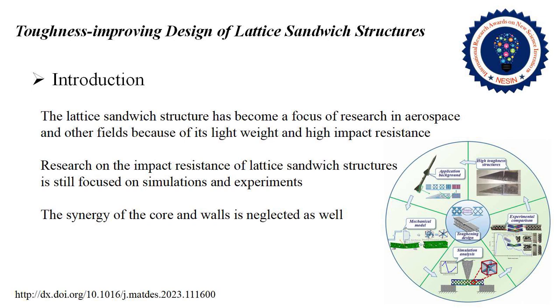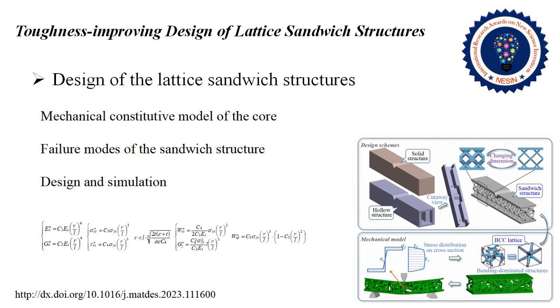To supplement the existing research work in the field of lattice structures, the mechanical characterization of the lattice sandwich structure is described. The finite element simulation method for toughening design is also provided, and the dimensional effect and the mechanism of synergistic toughening are studied. The high mechanical properties of the sandwich structure are derived from the porous core and the thin walls with a high elastic modulus. This structure places the walls in the state of plane stress. The porous core can not only change the whole stiffness of the structure, but also provide more deformation space. Benefiting from these factors, the lattice sandwich structure has high toughness and impact resistance.